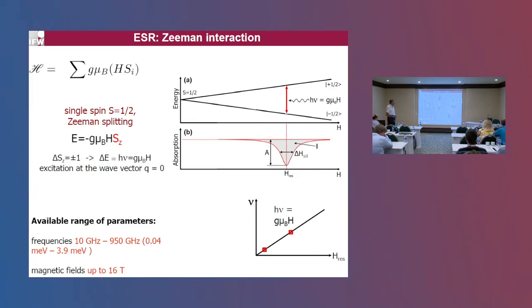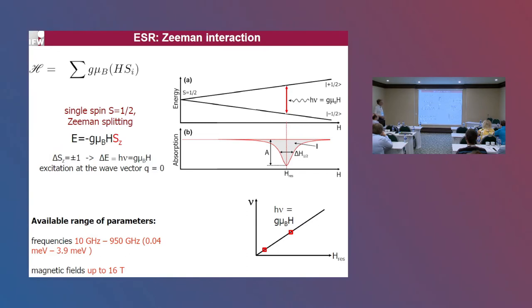The slope of this line is determined by the G-factor, a very important spectroscopic quantity — it relates the angular momentum of a quasi-particle with its magnetic moment. In our lab, we can change the excitation frequency by two orders of magnitude, from 10 GHz to almost 1 THz, corresponding to energies from 40 microelectron volts to almost 4 millielectron volts. This is the relevant energy scale for looking at spin waves.